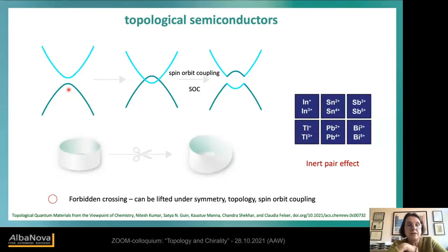So if we have sodium chloride, we have ionic crystals, we have a large band gap. Therefore sodium chloride, the salt you have on your table, is wide, while other semiconductors where the bonding is much more covalent and stronger have a small band gap. And what can happen is also that the band gap becomes even negative, so we have an overlap between the conduction and the valence band, and this is if the bonding is very weak, and also if the elements become heavier, they are bigger, so the bonding becomes less strong.